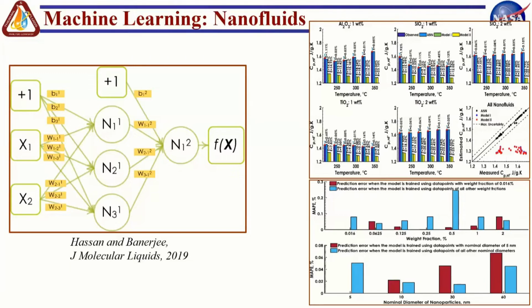So we did some preliminary study to predict the heat capacity of molten salt nanofluids, primarily nitrate salts or solar salts that are typically used in solar thermal applications. And the picture on the right shows a typical artificial neural network, a multi-layer perceptron model that we used in our prediction models. Without getting into too much detail, I can answer questions on the computational procedures.